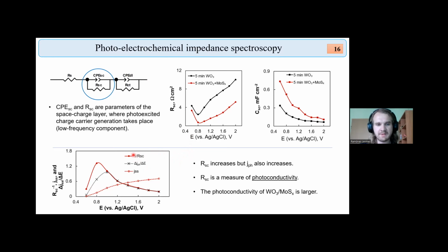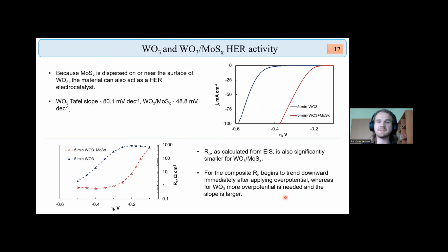And we show this by plotting the inverse of the space charge layer resistance and by calculating a sort of rudimentary derivative by dividing the photocurrent by applied potential. And we obtain a very similar tendency, for which a lot of the points even coincide. So with this, we claim that the Rsc is a measure of photoconductivity. And that means that the photoconductivity of these composites is larger, that means more photoexcited charge carriers are generated within the space charge layer.